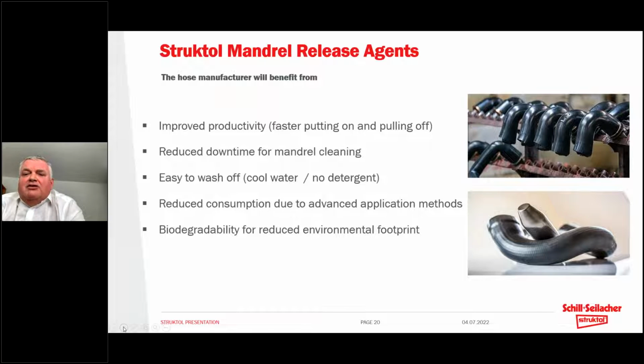So yes, in summary, these products really are designed to improve productivity, so they improve the installation of the hose onto the mandrel and therefore reduce the downtime for mandrel cleaning. They eliminate mandrel fouling, are easy to wash off, and the newer application methods reduce the consumption. We can really optimize the dosage in terms of how much mandrel release we need to apply per hose. And as mentioned, the products should all be biodegradable. Next slide, please.